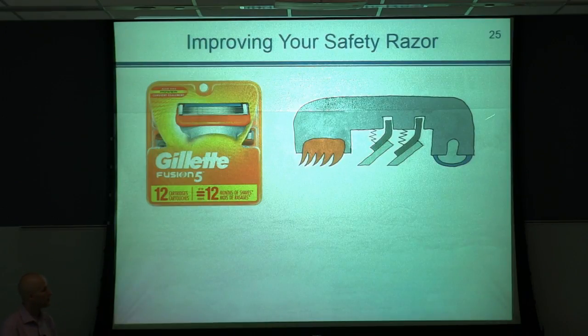Now, this is the schematic. These are the blades that actually do the work, and this is a schematic representation of the skin stretching element that needs to have high friction. So we have high friction here, which is required, and we have low friction here because this second, as they call it, guide, is covered by a lubrication layer, a sort of gel that generates low friction, and then the device operates well. However, what happens after about a month, when this layer is removed? Then we have high friction here, skin is not stretched in between these two guides, and the blades start cutting skin that creates a wavy shape.